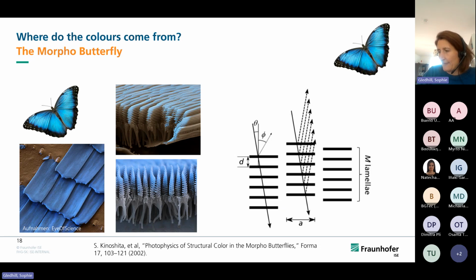And he described the effects using a basic model consisting of infinitely thin and equally spaced lamella in air, which causes a Bragg reflection effect. Furthermore, the lamella have a limited width and a randomly distributed vertical offset to the neighboring lamellar stack. This causes diffraction and results in an angular distribution of the reflecting light.